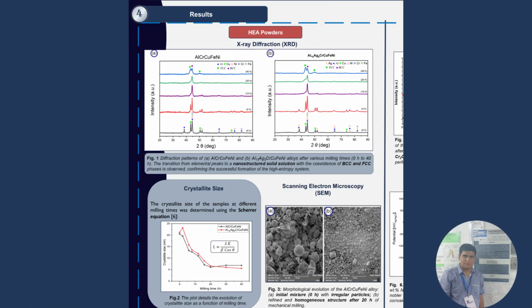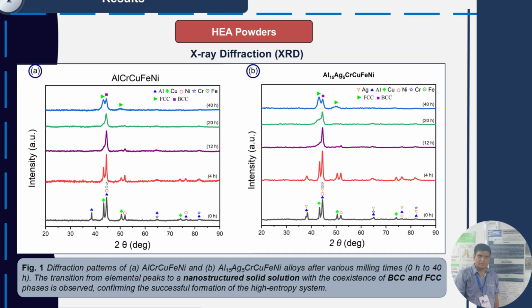Let's dive into the results, beginning with the characterization of the synthesized high-entropy alloys in powder form. If you look at the X-ray diffraction patterns on the left, we can trace the structural evolution from 0 to 40 hours of milling. As milling time increases, the sharp individual peaks of the elemental metals gradually disappear and broaden. This confirms the successful diffusion and transition into a nanostructured solid solution with the coexistence of BCC and FCC phases.